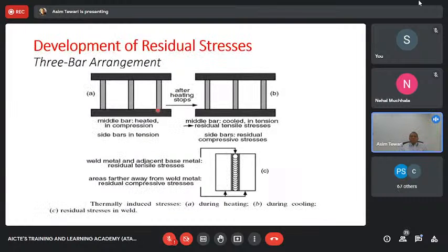So this is a very simple model, and I will be talking about a more complex part of it when we get into the finite element based modeling of this. So this is a very, very simple 3-bar model, which is very often used in welding. What this model says is how the welding is going to result in residual stress. The question is, when you're welding two parts, let's say you're not adding any filler material for the sake of simplicity. Let's just say you're just heating a part, and that part gets heated up, then it melts, then it solidifies, and that's it. Now, you expect it to have residual stresses. The question is, do you really expect it to have residual stresses because you heated it up from room temperature to high temperature, and then you cooled it down from high temperature back to room temperature?